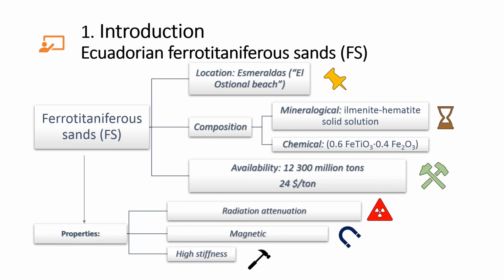In Ecuador, these sands can be localized primarily along its Pacific coast with an estimated commercial value of $24 per ton and have been conventionally used only as a cement clinker additive and agro-industrial fertilizer. Recently, these sands have been employed as a low-cost precursor for the synthesis of iron titanium oxide-based nanostructures via soft chemistry approaches. However, applications of Ecuadorian ferrotitaniferous sands without chemical treatments have still not been reported in the literature as far as we know. A previous study determined that these sands are an ilmenite-hematite solid solution.